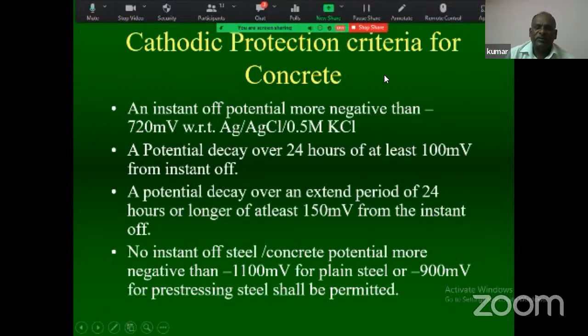The cathodic protection criteria for concrete. So here the potential is very, very important. If you are measuring the initial open circuit potential as minus 240 millivolts with respect to the saturated calomel electrode, you have to shift it a little more negative, for example 100 millivolts, and it is getting protected. For that, you can add an external electrode, either a sacrificial or an impressed current system. For example here, more negative than minus 720 millivolts with respect to the silver chloride electrode. For the potential decay over 24 hours, a 100 millivolt shift is more than enough. These are the phenomena people are using.